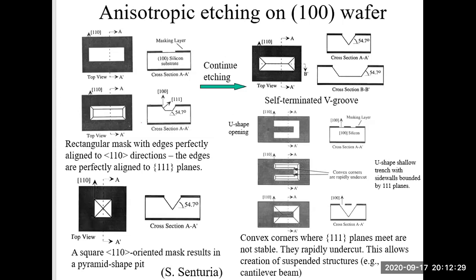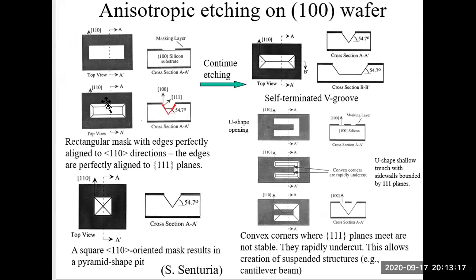If we continue etching, what will happen? Let's focus on this cross-sectional view. These two planes are 111 planes, so they will not be etched. The etch will only proceed in the vertical direction. So eventually, these two 111 planes will meet with each other. Or we can see that the two 111 planes on the long sides meet with each other, and then eventually we obtain a V groove.